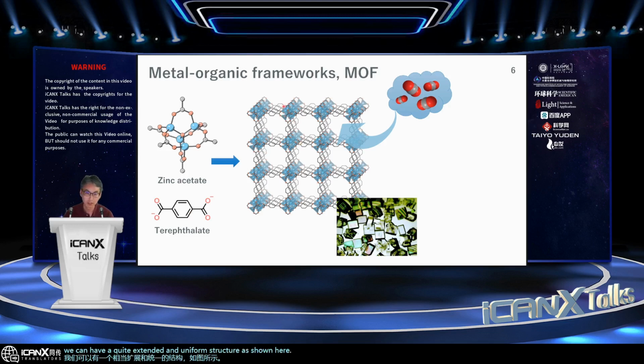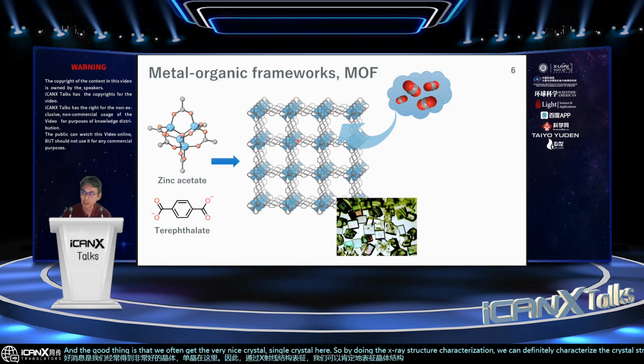So you can take a look. This blue one is a zinc metal cluster, and each of them is bridged by terephthalate. You can see the benzene ring in between. And the good thing is that we often get very nice single crystals, which I'll show here. By doing X-ray structure characterization, we can definitely characterize the crystal structure as shown here. Based on this crystal structure, we can imagine what kind of materials application can be expected.